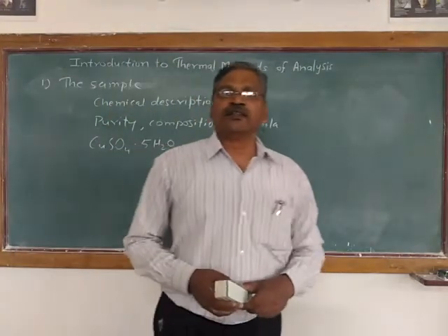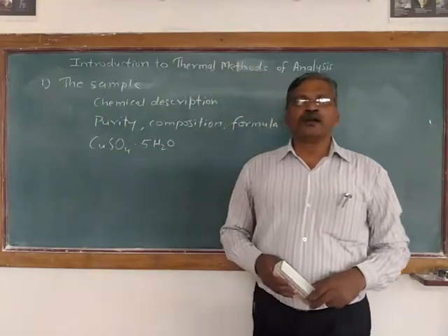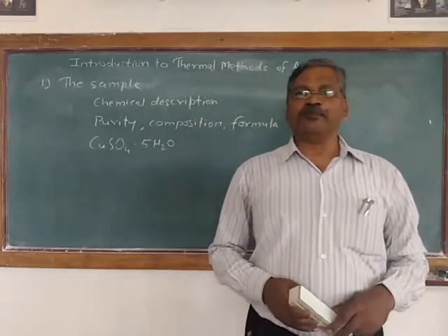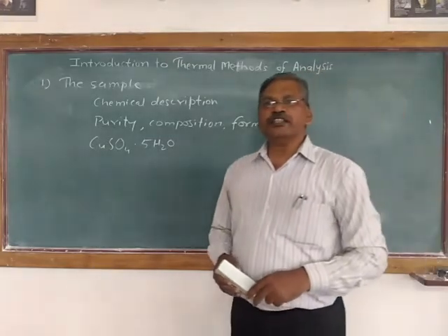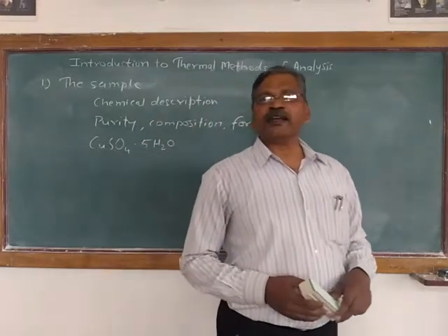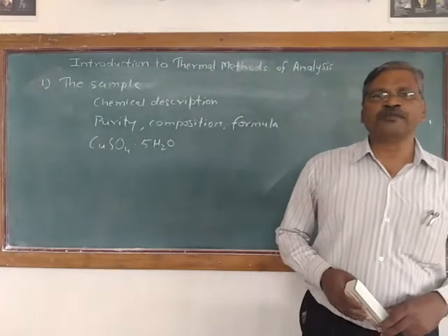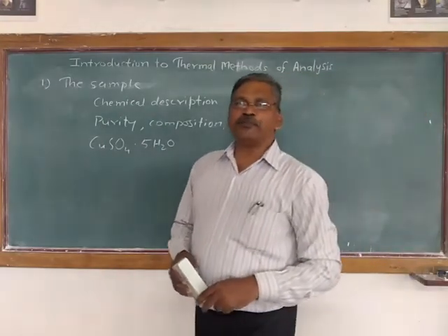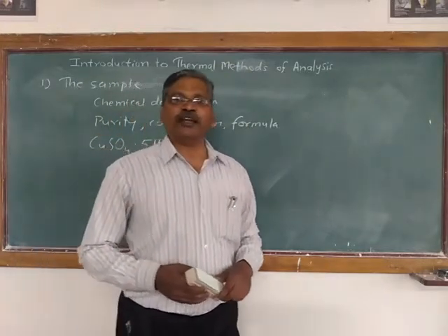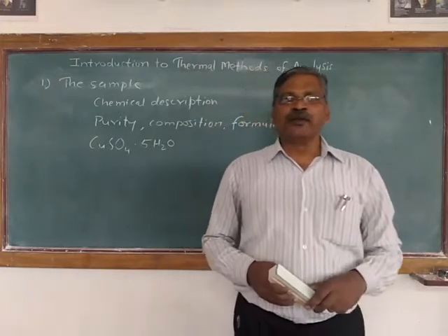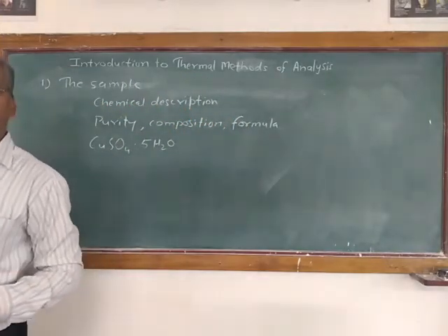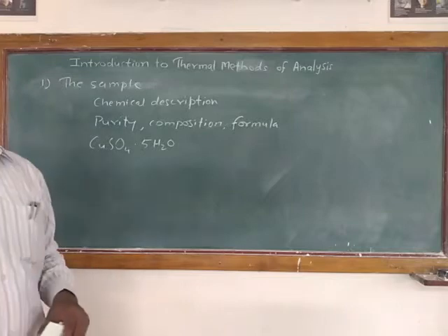All these factors could affect the thermal analysis curve. A change in the chemical composition would alter the decomposition of the copper sulfate sample, as would a change in the purity. The diluent will alter the heat transfer characteristics and the shape of the curve. The history of the sample, and possibly its method of preparation, can also affect the thermal analysis curve. Trace amounts of impurities can catalyze the decompositions and cause different reaction sequences.